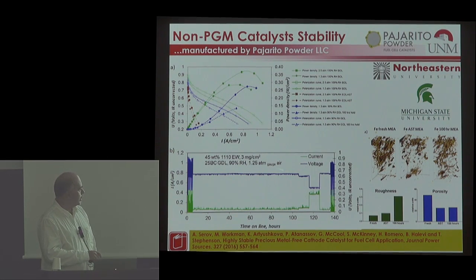And it's also illustrated by a relatively small loss of activity under the DOE protocols of operation. Many industrial partners would like to see these hold-up tests, and the Department of Energy wants to see these tests, with cyclic operation. So now what we know is what happens during this degradation. What happens is that the porosity of the catalyst changes. It redistributes itself. So the porosity actually decreases, and the roughness of the catalyst increases as you operate it.